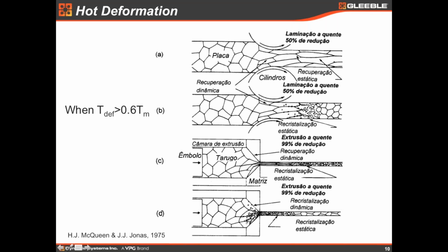So in this way, we see here that there is no grain boundary movement, just the grains are elongated, and we have softening by dynamic recovery in the deformation zone and static recovery after unloading. If we have a low stacking fault energy, let's say austenite, we have a deformation here, creation of dislocations and driving force, and during the interpass time after unloading, we have the nucleation and growth of statically recrystallized grains.